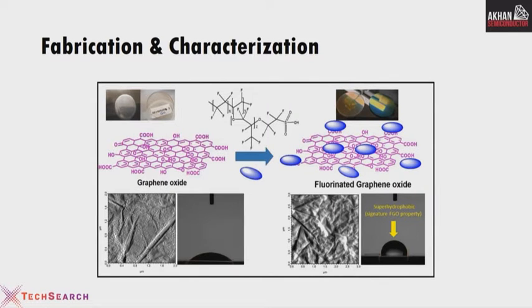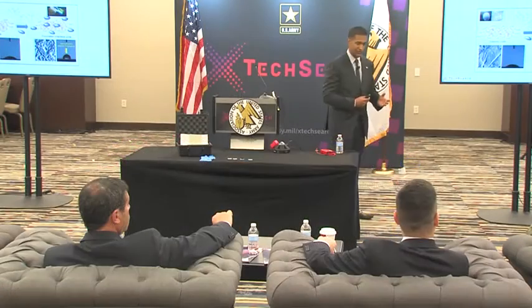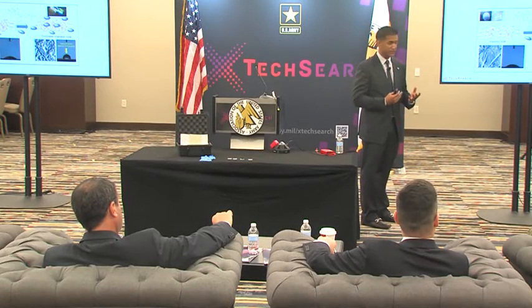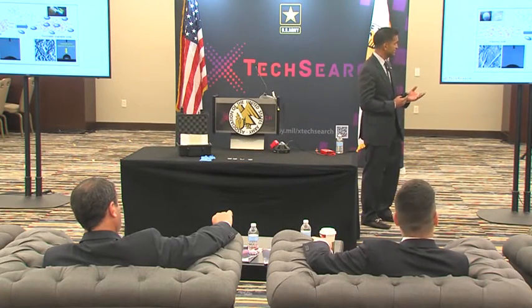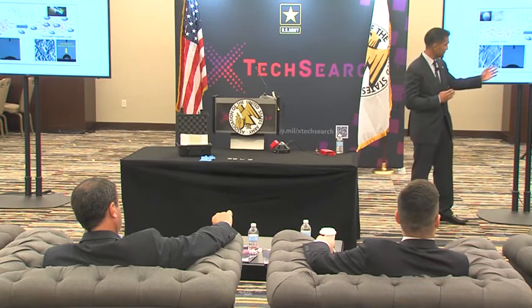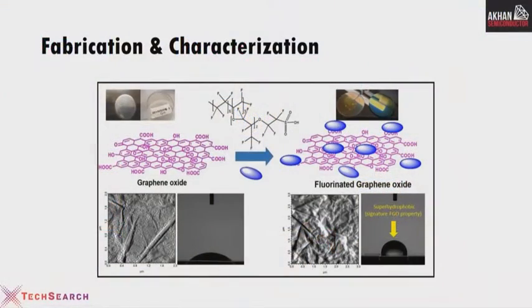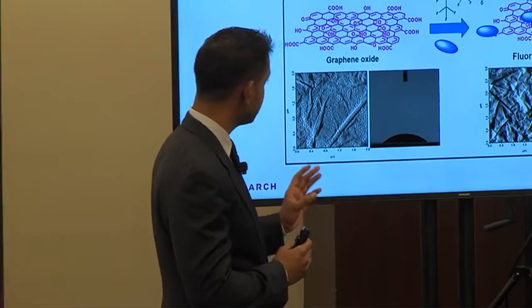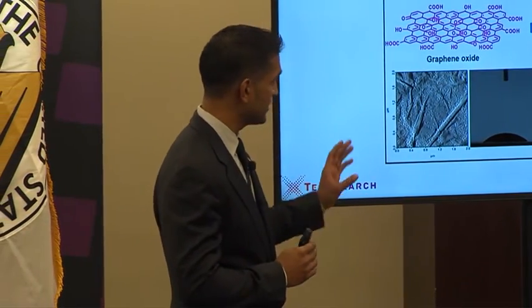So as soon as we saw this last image, we were very encouraged. As I mentioned, FGO is very, very difficult to synthesize. But as soon as we saw the water droplet move from a hydrophilic material to a super hydrophobic material, we knew we were about to see something very exciting. What we see here is the atomic force microscope image of the graphene oxide.